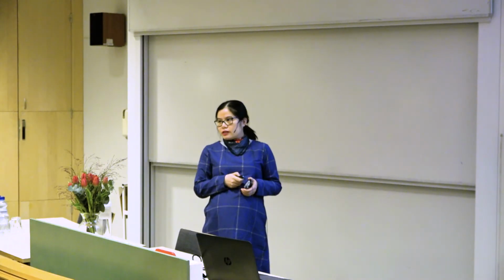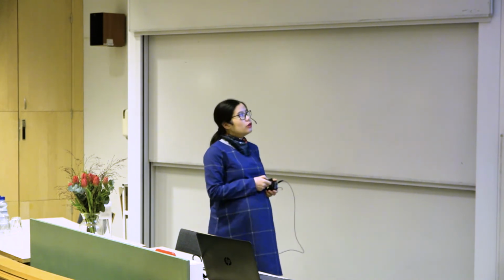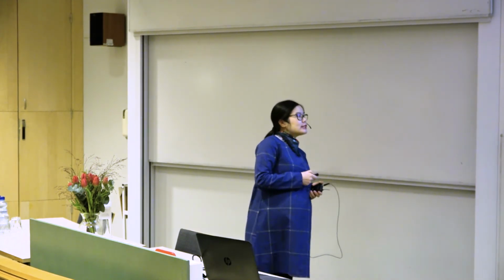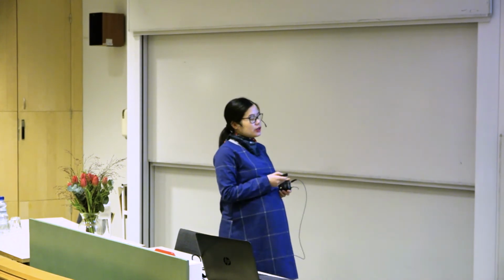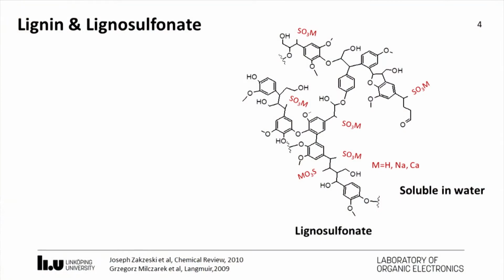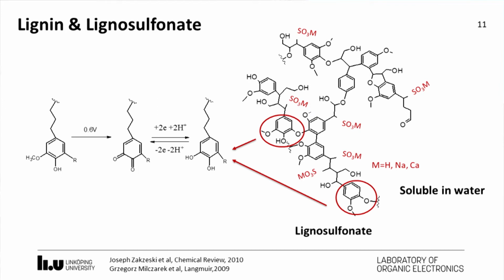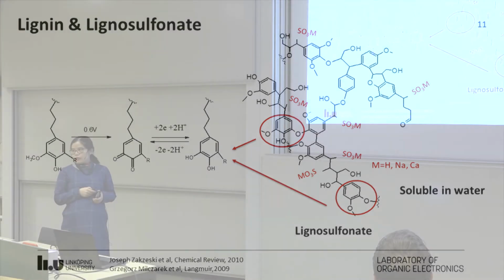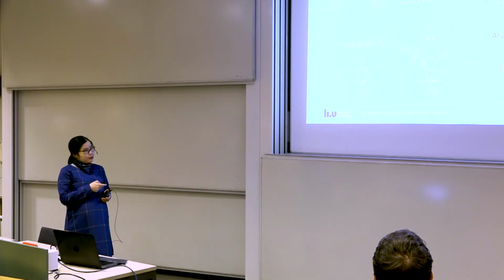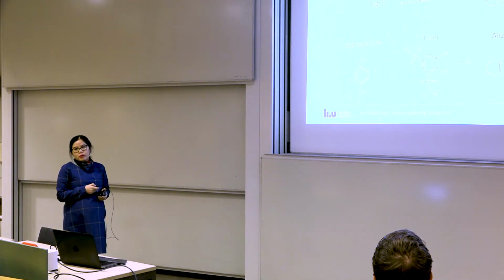The chemical structure of lignin differs from woods to woods, but in general, they have these complex network structures and it is insoluble in water. Sulfonated lignin, or lignin sulfonate, is soluble in water due to the introduction of these hydrophilic sulfonate groups. And upon oxidation, the phenolic moieties can be oxidized to these cyclic dione structures and can undergo proton-coupled electron transfer reactions reversibly. But you can see that there are also other electroactive groups, so the energy density of lignin sulfonate needs to be increased further. And this was also promising.